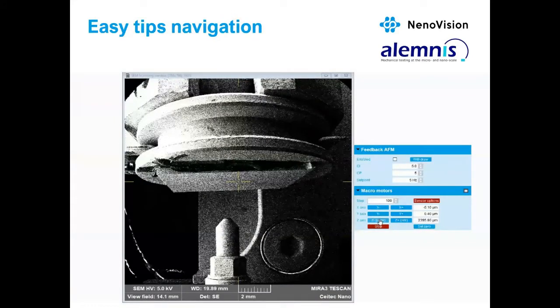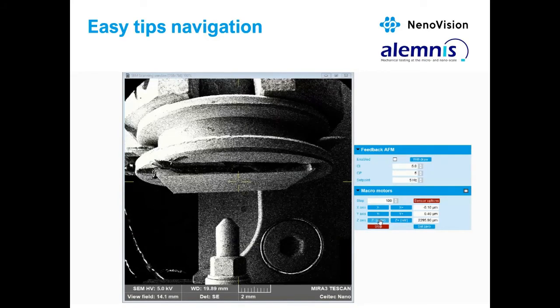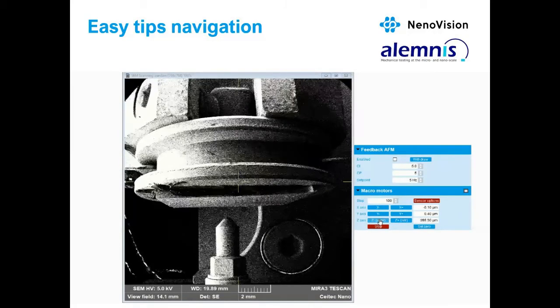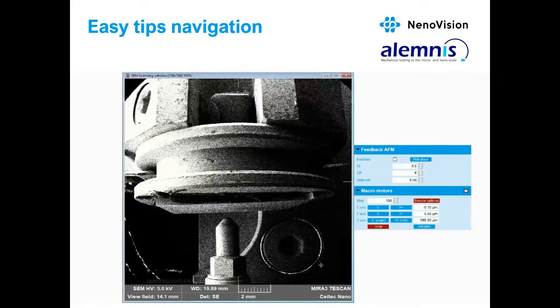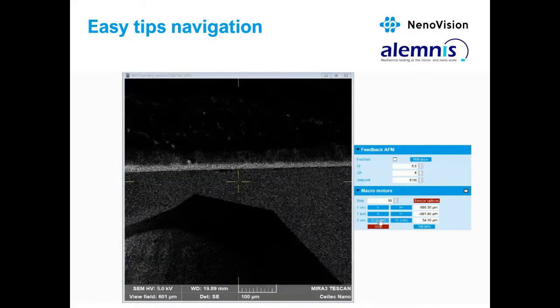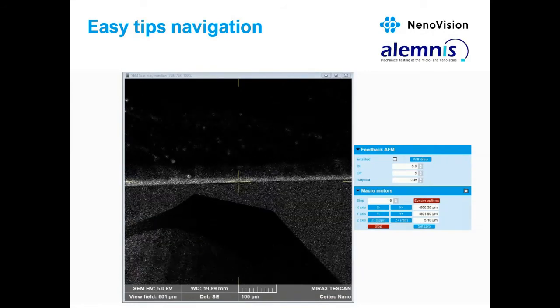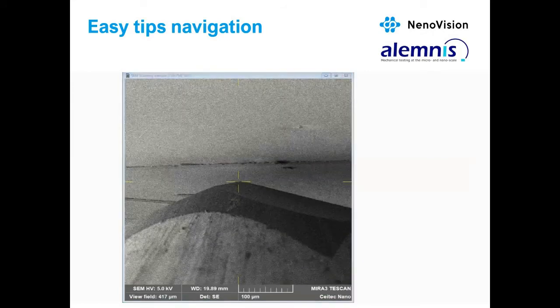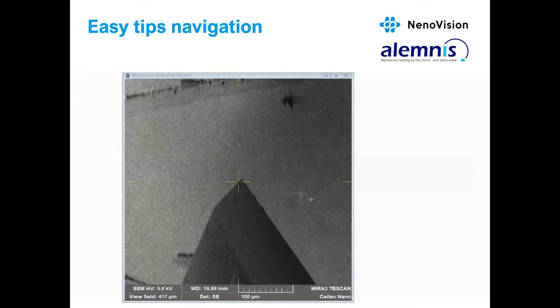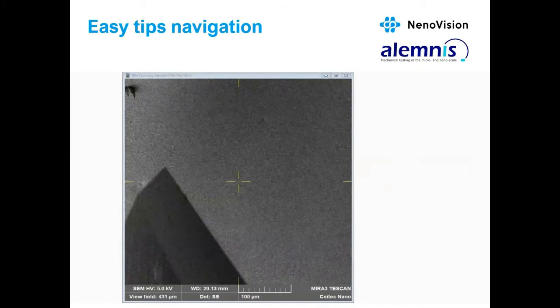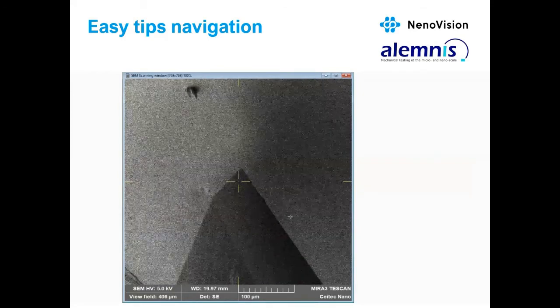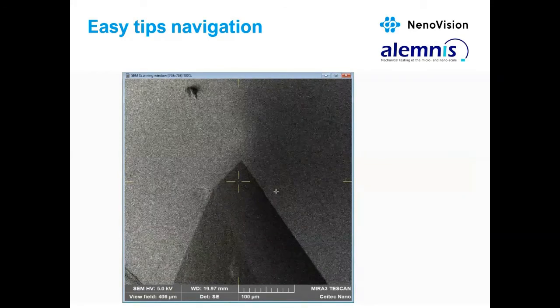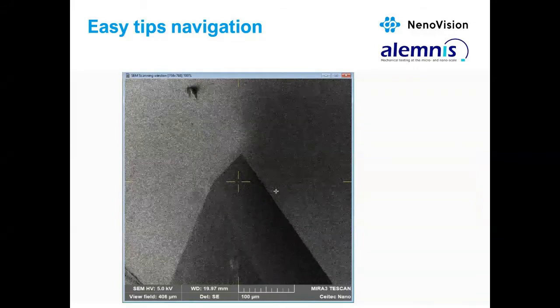To give you an insight into the measurement and interconnections of these devices, I would like to shortly show you the operation during the measurement. We first get closer with the sample to the indentation tip. It's quite easy because you can see all the time in the SEM. We find the spot to be investigated, and then we slowly get into the contact.